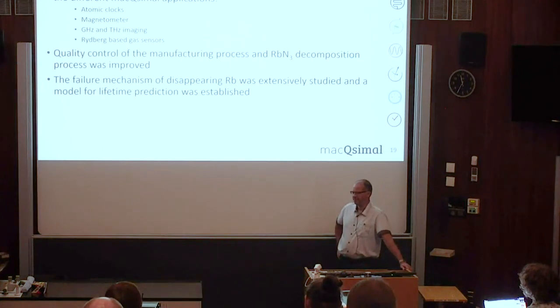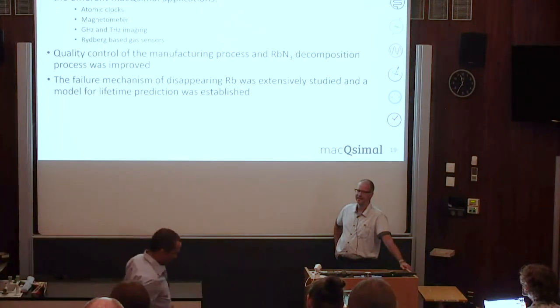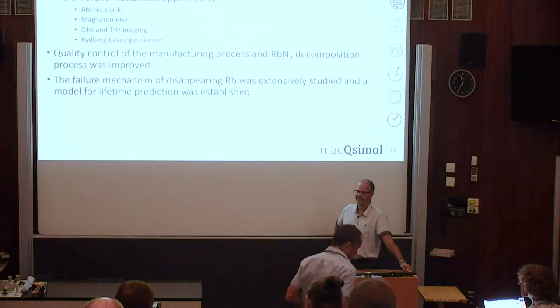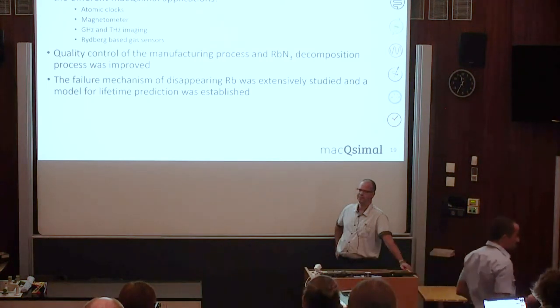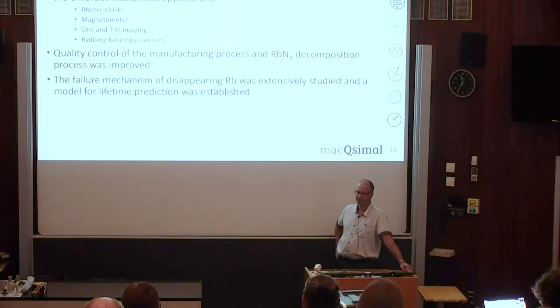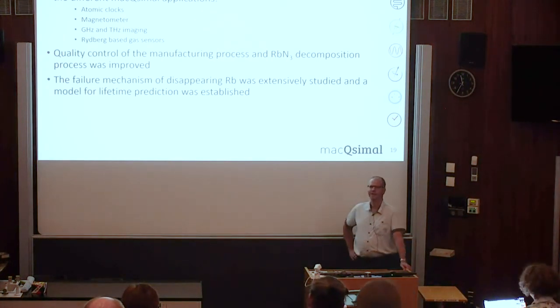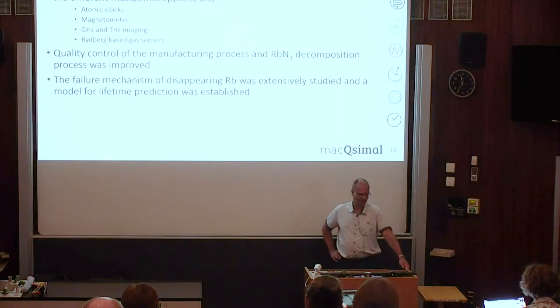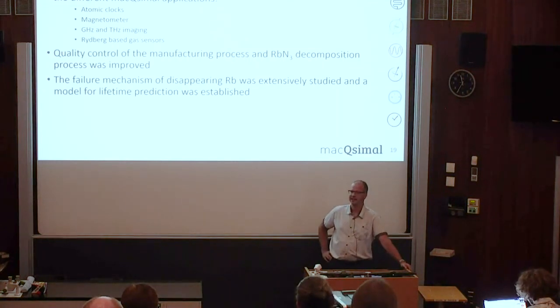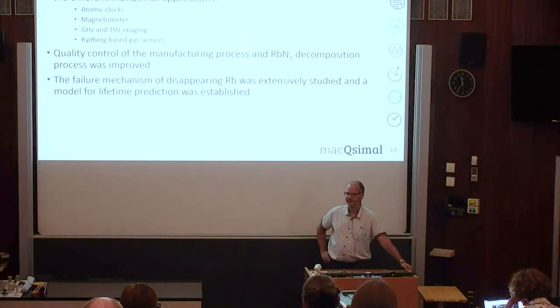So I would not recommend to use a ring because I showed you also the phase diagram, the binary phase diagram. So you have to know that the rubidium that makes the reaction with the gold is not usable anymore. So the quantity of gold introduced in a cell has to be very much below the quantity of rubidium. So if you make dots, this is better than a ring.